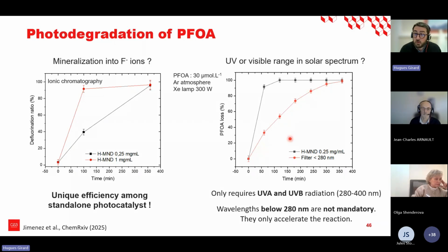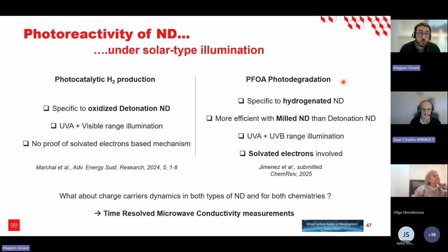Of course, if you add a little bit more deep UV, you're going to accelerate the effect. But even with only the UV which is present in the solar spectrum, you will have the effect, which is really good. So with that, I will conclude on this part on the photoreactivity of the nanodiamond, which is important. You can find all the details in this paper, and we just submitted a paper for the PFOA photodegradation, but you can also find the results on ChemRxiv. And so the question now is, okay, what about the charge carrier dynamics in these particles? And now I will leave the floor to Jean-Charles to continue this lecture.